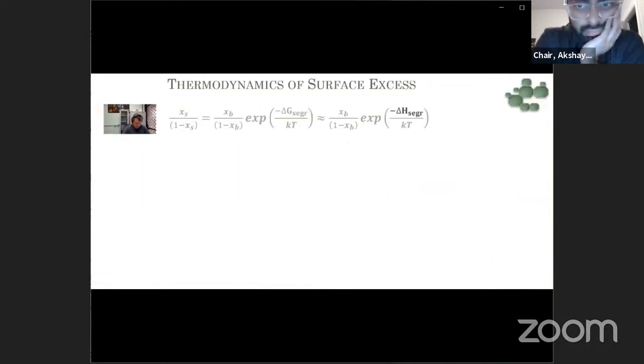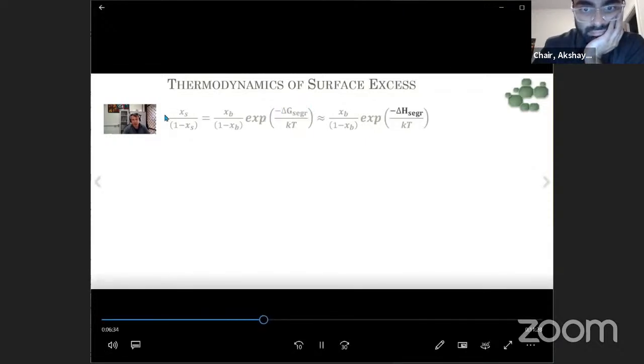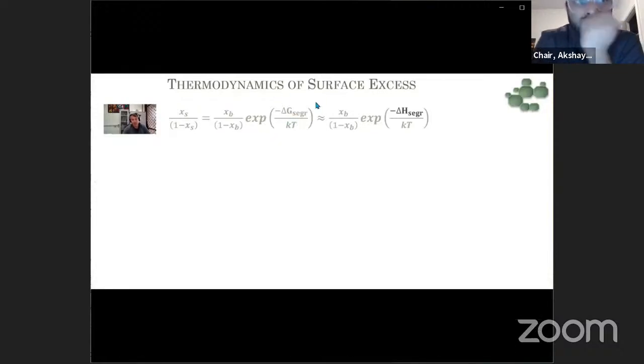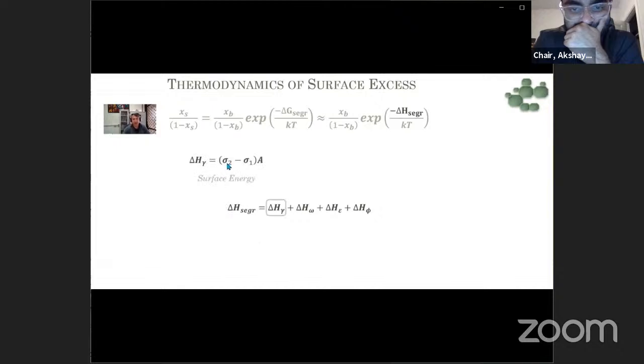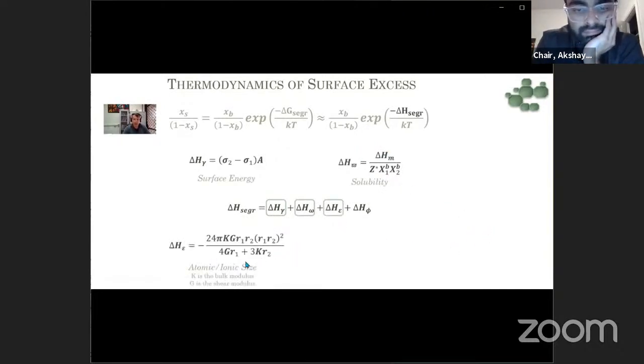Looking at the thermodynamics behind the surface excess, when you have a free energy of segregation, the concentration in the bulk and the surface are not the same. And the free energy of segregation is approximately the same as the enthalpy of segregation. The enthalpy of segregation has 4 components. The first one is the difference of surface energy between the solid and the solvent. The second one is related to the solubility. The third is the difference between the atomic size or ionic size. Then when you have a big difference between radii, it is easier to segregate. And the last one is the electric charge related to the charge of ions in the system, then related to the depletion layer.